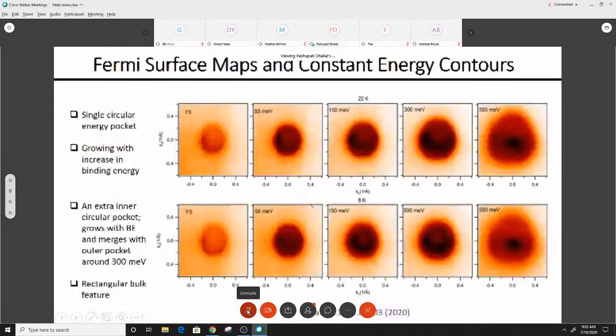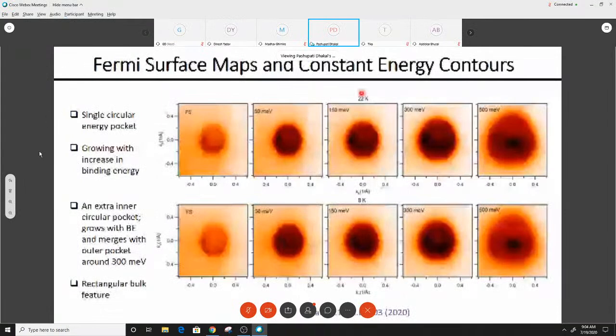Next, I move on to the results from our ARPES experiments. The upper panel shows the Fermi surface and the constant energy contours at various binding energies at 22 Kelvin, that means in the paramagnetic phase, and the lower panel shows the data in the antiferromagnetic phase at 8 Kelvin. In the paramagnetic phase, there is a single circular energy pocket which grows with increasing binding energy, implying the hole nature. In the AFM phase, in the lower panel, the hole pocket is still there.